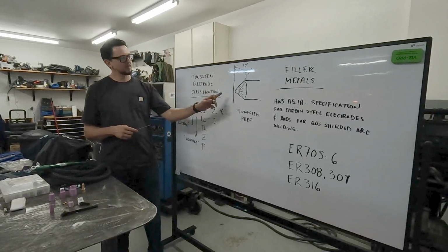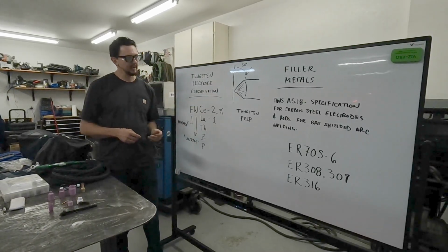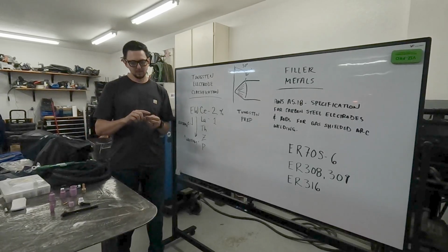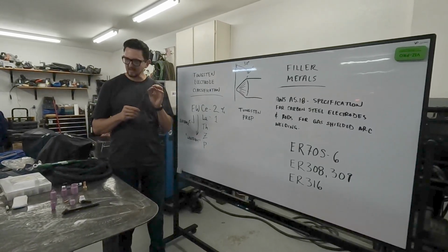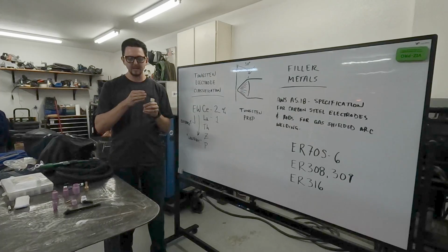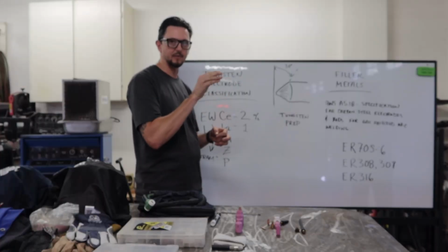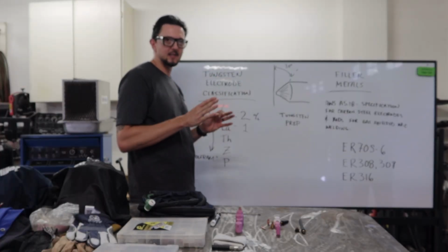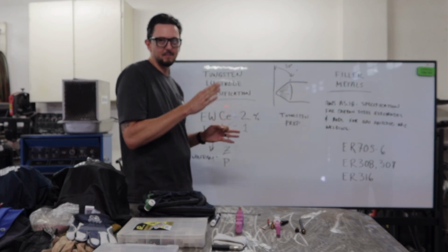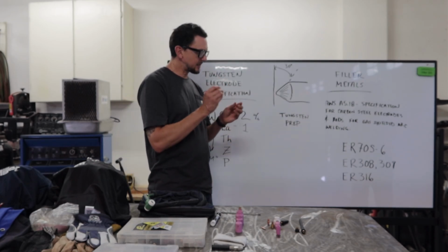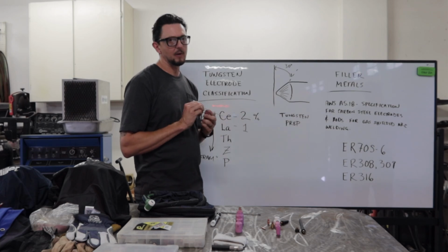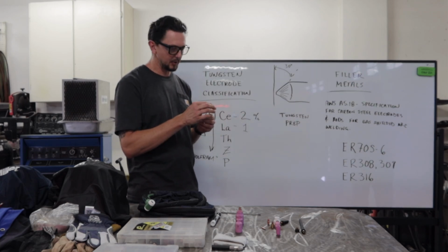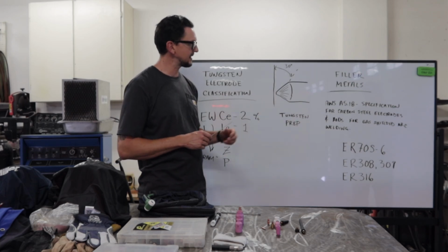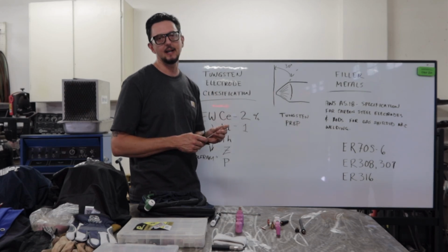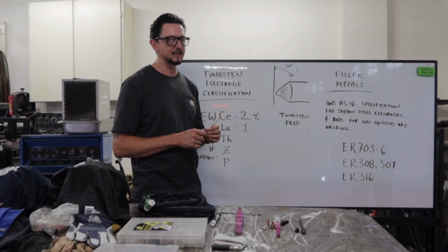And then typically I'll put a little flat at the end. If you were to grind this all the way down, and then you take a look at it with the microscope, at the very end it will actually have a little curve where it curls, which causes the arc to be a little bit uneven. So if you just barely touch that wheel at the end to put a slight flat on the end, then it'll be nice and even on both sides.